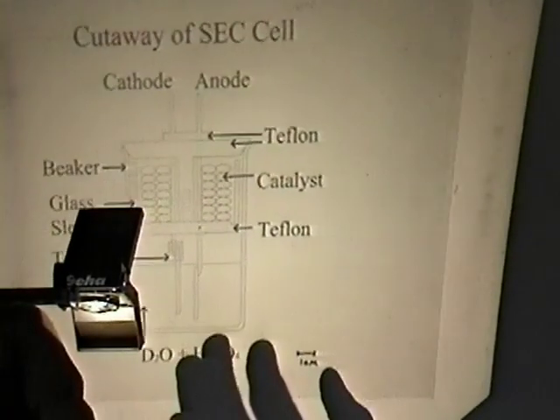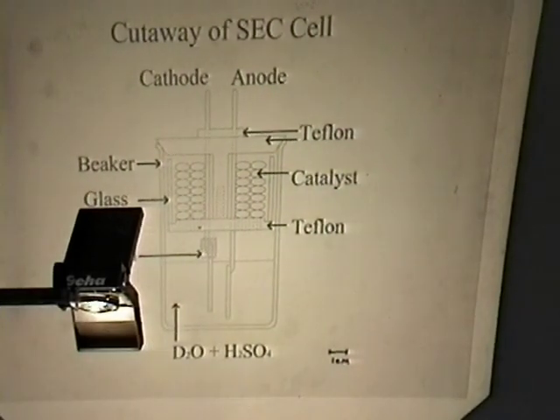The next system that we used is a Seebeck envelope calorimetry system by Thermonics Corporation of America. Now this allows us to scale up our experiment. You can see the scale here, the centimeters, is very much smaller than the previous. We can now use 75 grams of electrolyte, and we use about 20 grams of catalyst. We still have a titanium cathode attached to a platinum lead and a platinum anode attached to a platinum lead.